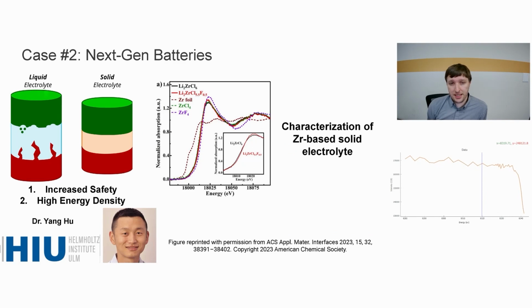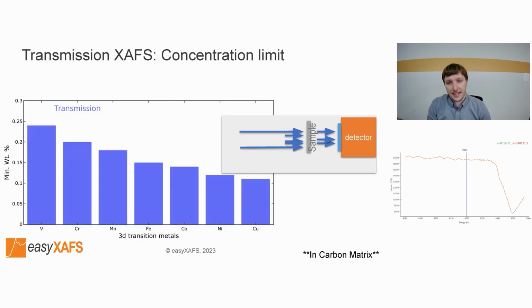In this recent work, Dr. Yang Hu supported the characterization of a zirconium-based solid electrolyte that was found to have increased long-term stability. In this case, XAFS was a helpful tool in the material synthesis process to identify changes in the zirconium environment with fluorine doping. So far today, we have provided highlights for transmission mode XAFS measurements.